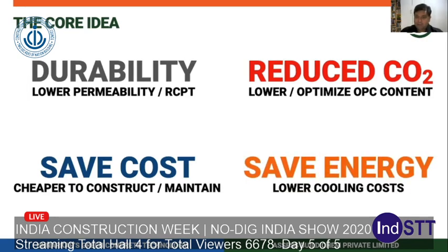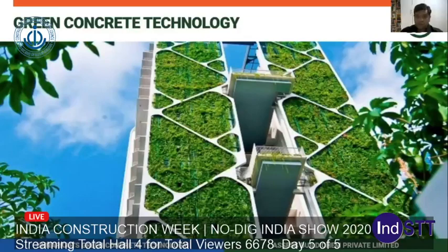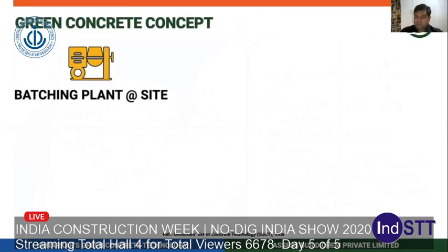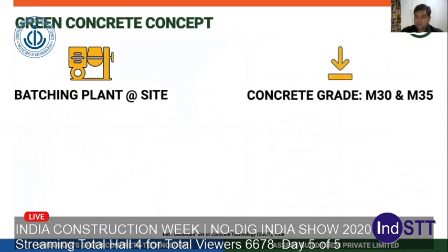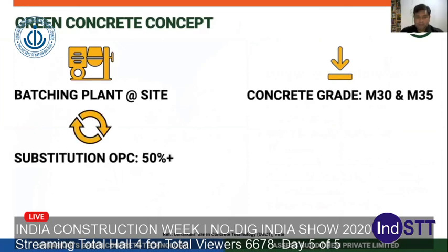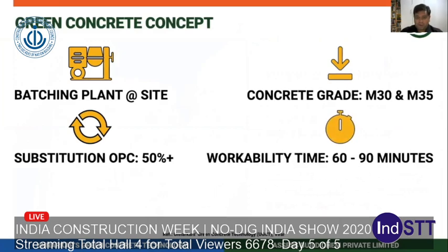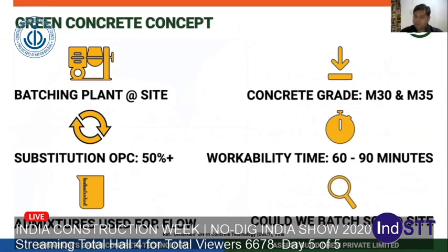Last but not least, of course, we make it sustainable by saving energy and lowering the cooling costs. So, talking a little bit about the green concrete technology, the concept came about when we started off making this concrete at a batching plant on site. What was targeted was concrete of M30 or M35 grade. The substitution of OPC was targeted to be 50% or more, with a reasonable workability time of about 90 minutes. Of course, admixtures were used both to reduce water, improve durability, improve the flow, and so on.